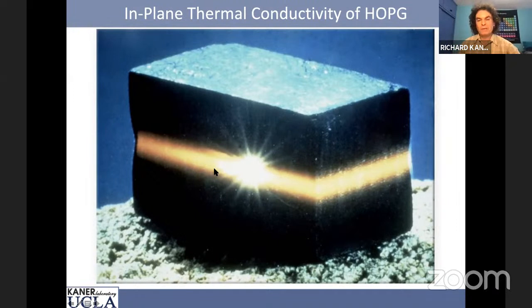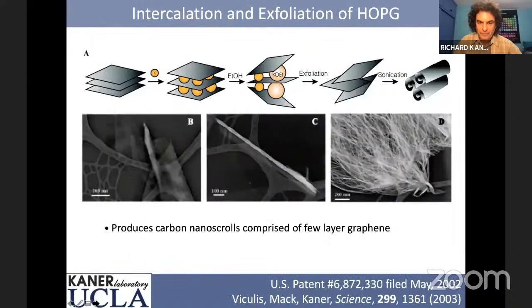That's basically because all the phonon modes, all the chemical bonds, the sp2 bonds, are all along the plane and they conduct heat, as well as the conduction electrons due to the overlap of the pz orbitals. They all conduct in this plane. So if you hit the laser here and you touch over on this side, you'll burn yourself, but if you touch the top, it's cold. A single layer is graphene, and graphene would show the same sort of property, except that this is a three-dimensional form of graphite.